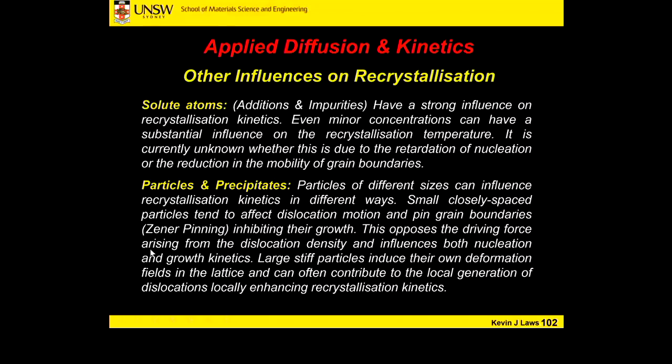So this opposing driving force arises from dislocation density and their influence on both nucleation and growth kinetics. Okay? Having those particles there, finely spaced and very, very small, can change and largely retard our recrystallization kinetics. However, large, stiff particles in our material are a little bit different. All right. So these induce their own deformation fields or stress fields in the lattice and can often contribute to the local generation of dislocations, which can enhance recrystallization effects.